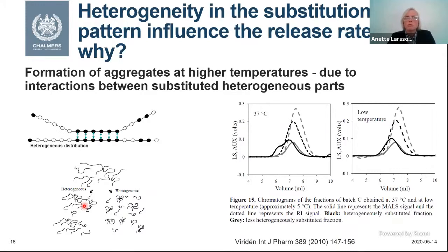That was also shown, as we were also making phase diagrams in another publication by putting a centrifuge in the 80 degrees oven. And I should say that this is an experiment that works quite well until the centrifuge breaks. But still, it costs a centrifuge. But it was good from that point of view that we could prove that this is really the case, that we have interactions in these batches, more strong interaction between these substituted regions.